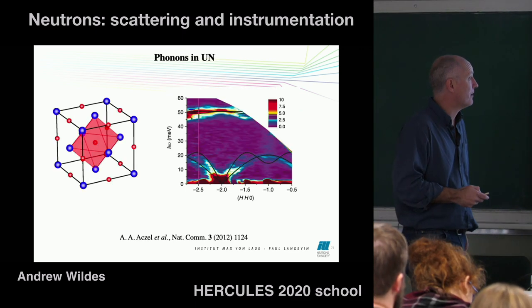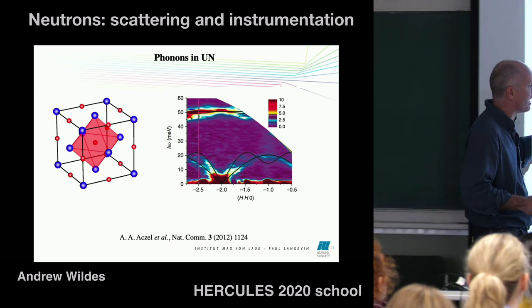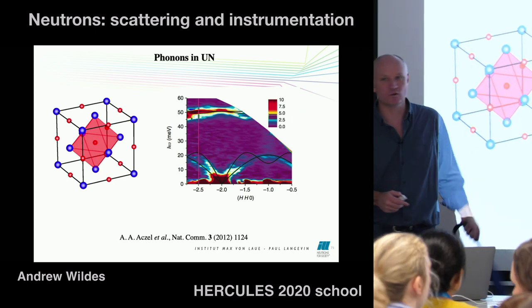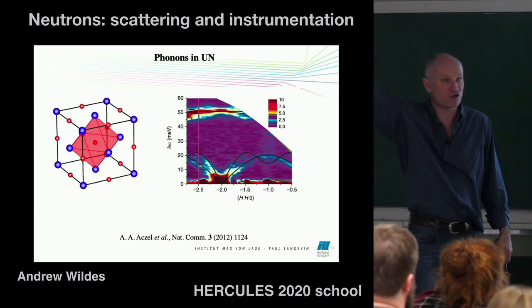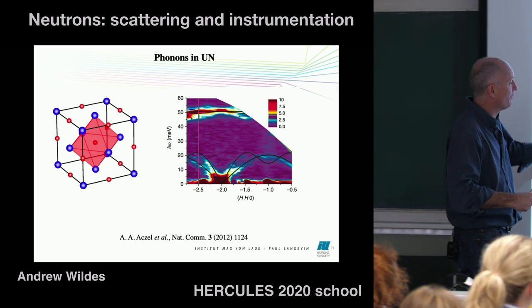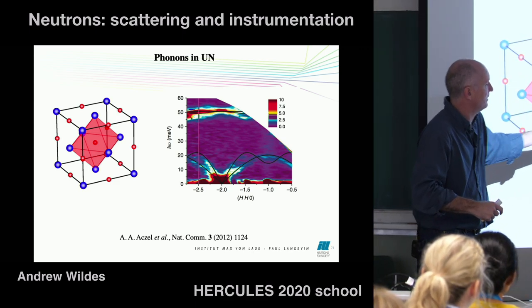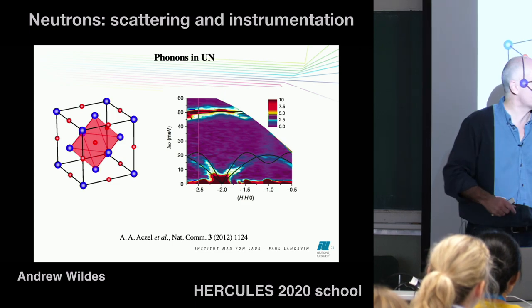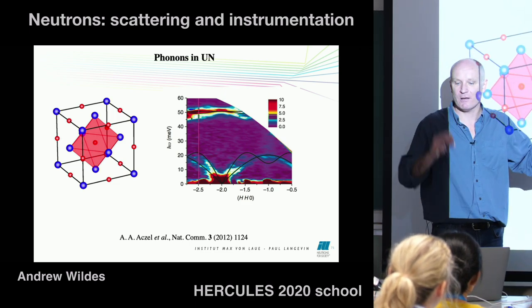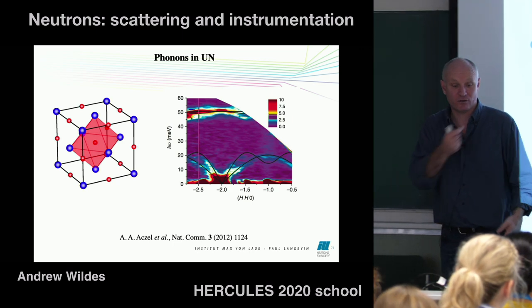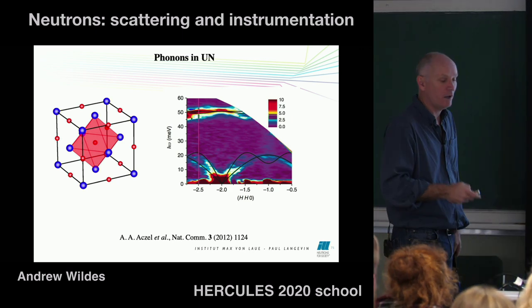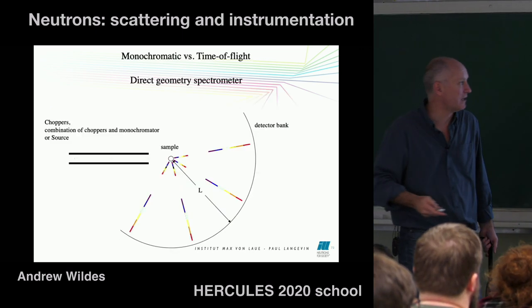If you do that, then you're able to cover something looking like this. This is a rather specific direction in reciprocal space. It's along the HH0 direction in reciprocal space. And what they've done is sort of gone all the way up here and all the way along here. You're able to cover out all of this, but it's this one here, you would have to measure point by point if you did it on a three-axis. You could also do this in time of flight, but it becomes a bit more complicated.